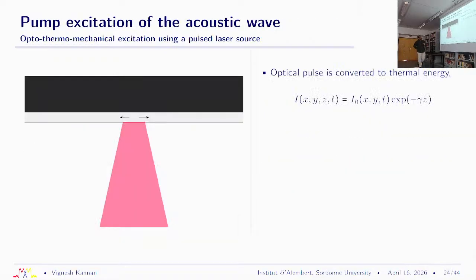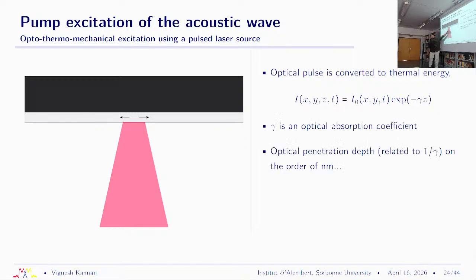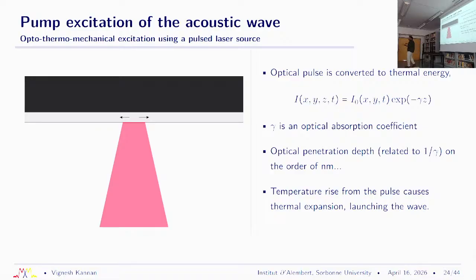So the mechanism for excitation, the one thing I forgot to tell you is once we finish etching our silicon film, we actually deposit a very thin layer of aluminum on the back and the top surface. So we're talking about a 10 micron sample and about 30 to 40 nanometers of aluminum on the back of the sample, right? So you have the excitation that comes in, right? The pulse laser basically creates an optical to thermal expansion on your aluminum film, and that results in the excitation of a wave through your silicon wafer. I'm not going to go into details for the lack of time, but we can always discuss the details of the excitation soon enough. But what you get is an excitation amplitude of something like 1 to 20 nanometers, depending on the intensity of the source you're sending in. Okay.